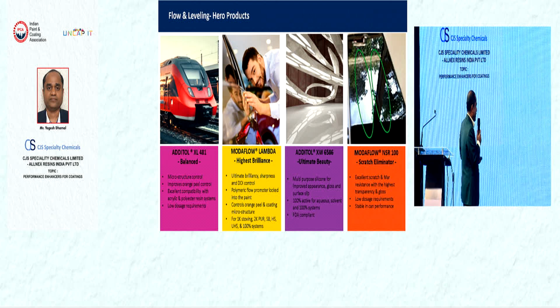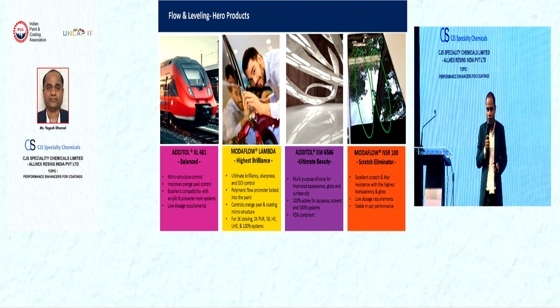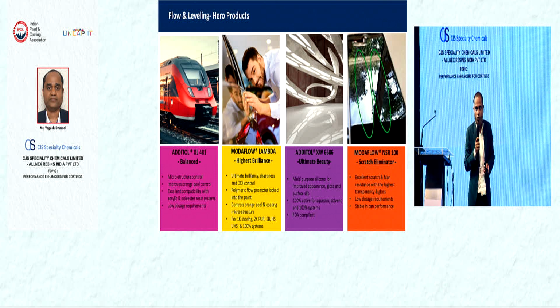Then MODAFLOW Lambda has ultimate brilliancy, sharpness and distinctiveness of image control. It is a polymeric flow promoter locked into the paint. It controls again orange peel and microstructure, and it's recommended for 1K stoving and 2K polyurethane systems. Next product is ADDITOL XW6586. It's a really beautiful product. It has multi-purpose applications. It is a non-reactive silicone for good slip and smooth leveling. Then MODAFLOW NSR 100 is a scratch eliminator. This is a nano silica additive. It has been recommended to improve the scratch resistance of your automotive OEM or vehicle refinish coating systems.